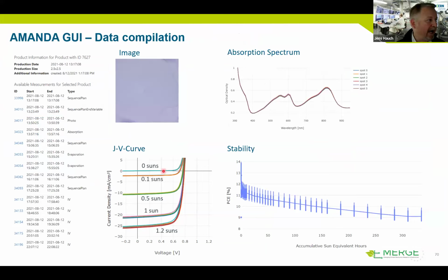Then what do we get back? Here's an example of the data sets that we create. Every sample has its unique ID. Here's a list of activities that were performed with the sample. We have an image of the layer. We have an absorption spectrum of the different layers. We have JV curves that we took of the devices. We have stability measurements, and all this is in a database. And this database is actually connected to another system that allows us then to model all these curves.